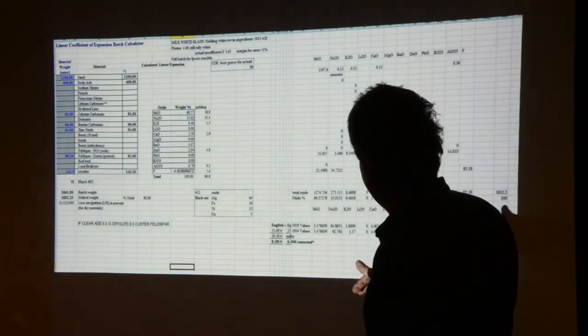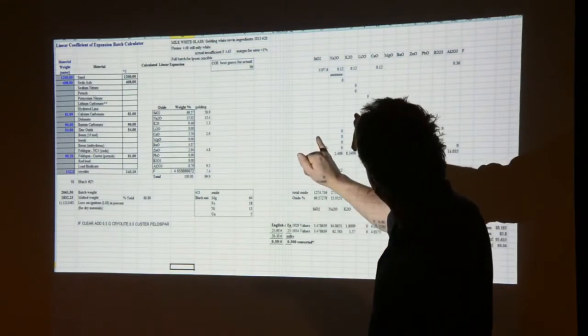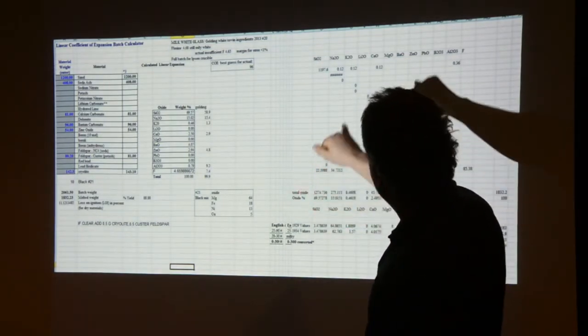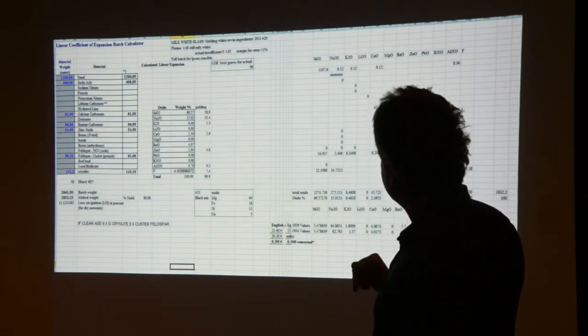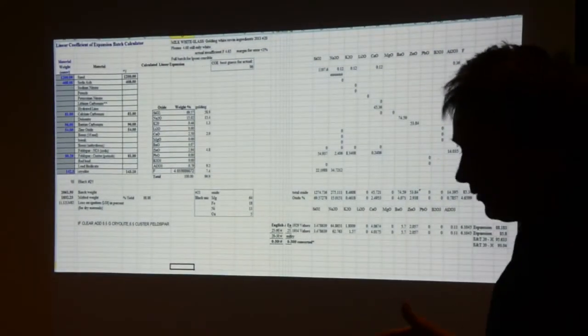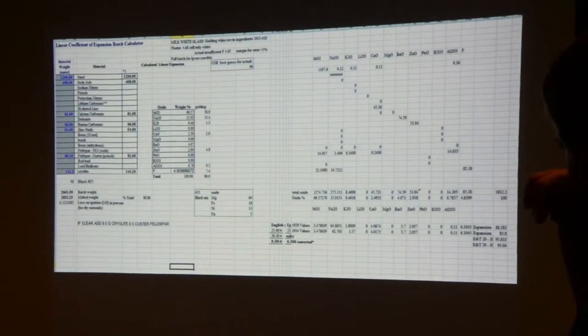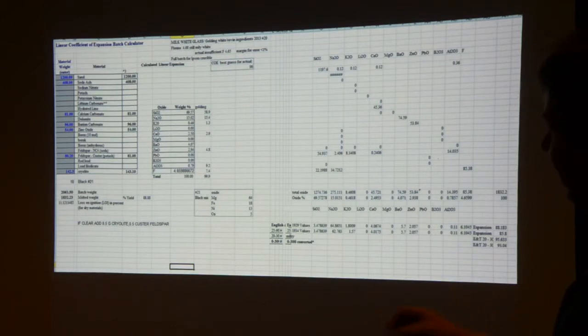The expansion coefficients, English and Turner values, are like 100-some years old, where each of these ingredients has a different value. So this silicon is fairly low, the lowest of them. Sodium is the highest of them. It's like 4 times, or a little more than 4 times the silicon. So how much sodium you add is going to make it a more expansive glass. And if you want to change over from 96 to 90, you're going to want less expansion. So you're pulling out some sodium, putting in a little more calcium, or just leaving sand. You've got some latitude there. So this kind of calculation process is very handy.